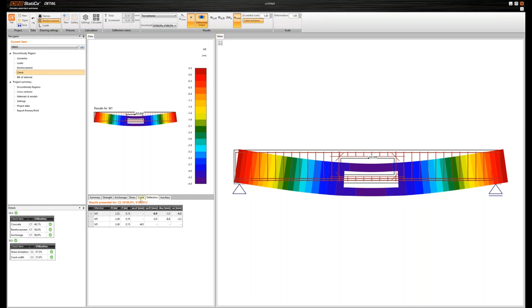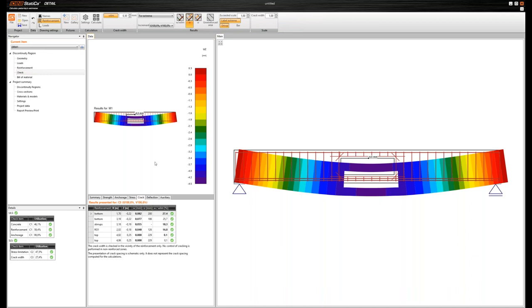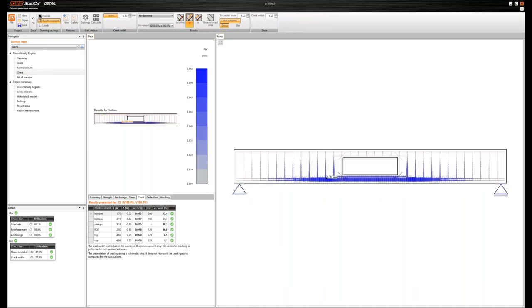which is very important. And again, let's move to the cracks, where we can see that due to this reinforcement, cracks were reduced. And this time I can also display the cracks in the region of the opening, where again I have low cracks. So this time I'm sure that I'm checking the crack around the opening.